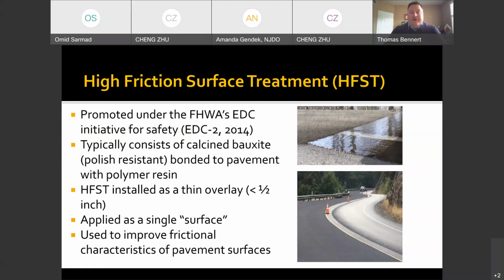So if you're not familiar with high friction surface treatment, really what it appears to be here is we're essentially gluing hard angular stone to the pavement surface. This was developed and promoted under Federal Highway's Everyday Counts program. In fact, this was in the EDC2 back in 2014. And the aggregate of choice is generally what we call a calcined bauxite. This is a very hard, very angular stone. It's actually heat treated to increase its hardness. So it's very polish resistant.